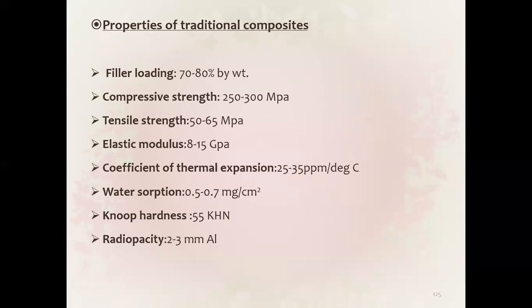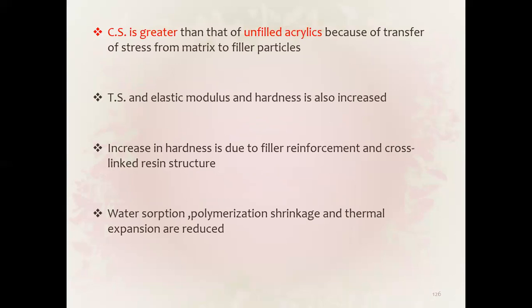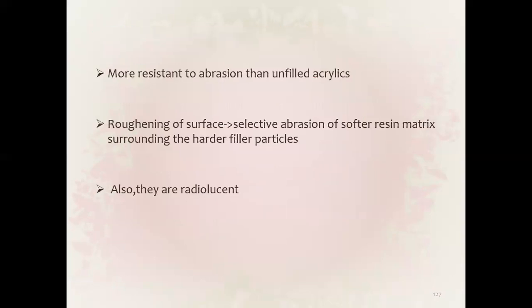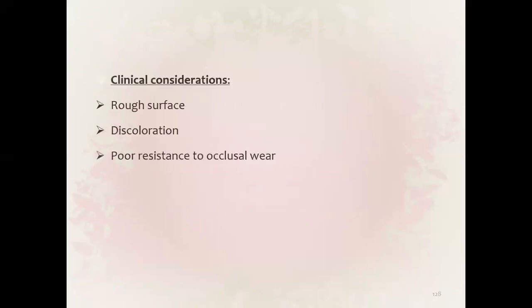Further properties of macrofill composites: water sorption 0.5–0.7 mg/cm², Knoop hardness 55, radiopacity 2 to 3 mm Al. Compressive strength is greater than unfilled acrylics due to transfer of stress from matrix to filler particles. Water sorption, polymerization shrinkage, and thermal expansion are reduced. Clinical considerations: rough surfaces, discoloration, and poor resistance to occlusal wear. The surfaces are radiolucent.